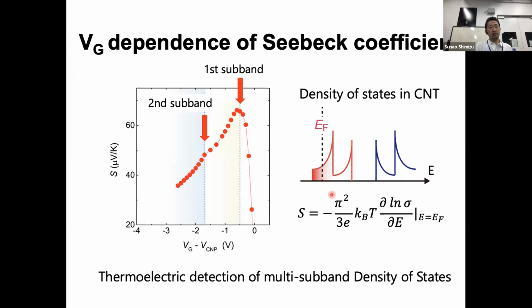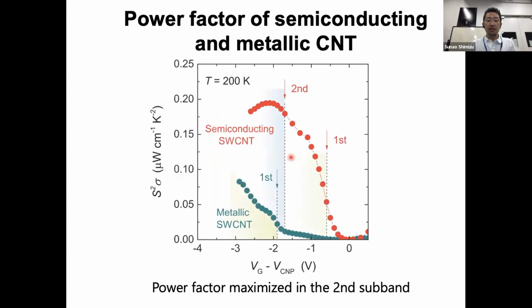We measured the Seebeck effect and also resistivity as a function of gate voltage or carrier density, so we can estimate power factors, which is a very important property of materials. This is the result, the power factor as a function of gate voltage. When we reduce the gate voltage, the power factor increased like this, and then finally shows the maximum in the second subband region. So we successfully optimized the power factor in the carbon nanotube thin film, which is very difficult to achieve by a conventional bulk chemical doping technique, because it is very difficult to dope or inject a lot of hole carriers like this. So we can apply this technique to other materials also.